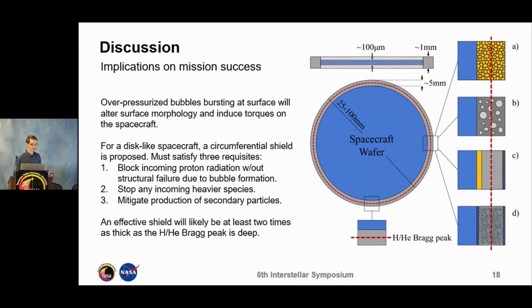So for a disk-like spacecraft, we propose a circumferential shield, which must satisfy three main requisites. The first is that it must block any incoming proton radiation without structural failure due to bubble formation. The second is that it must stop any incoming heavier species, such as carbon, oxygen, or iron. It also must mitigate the production of secondary particles, such as neutrons and Bremsstrahlung X-rays.